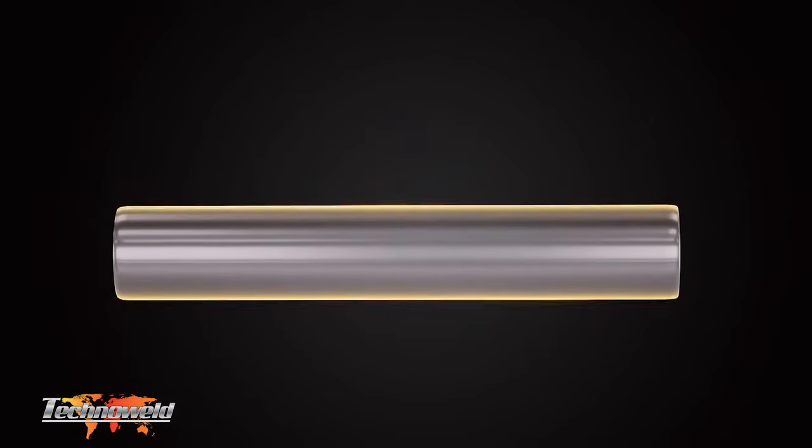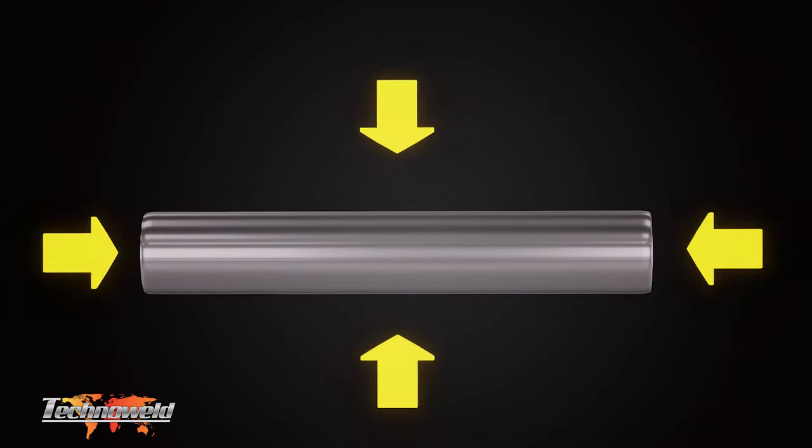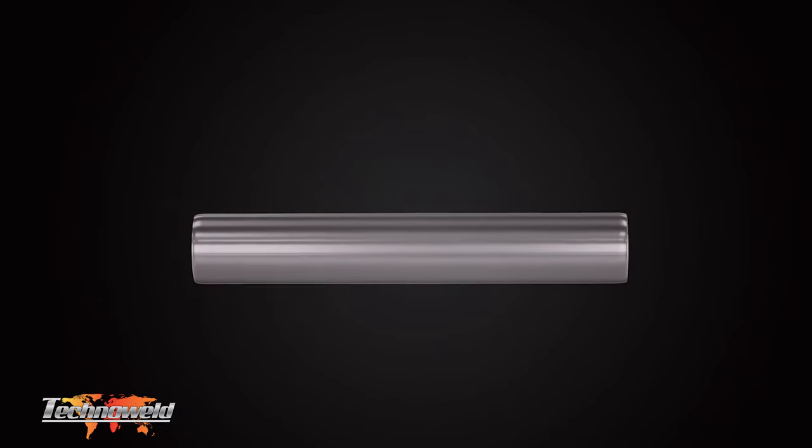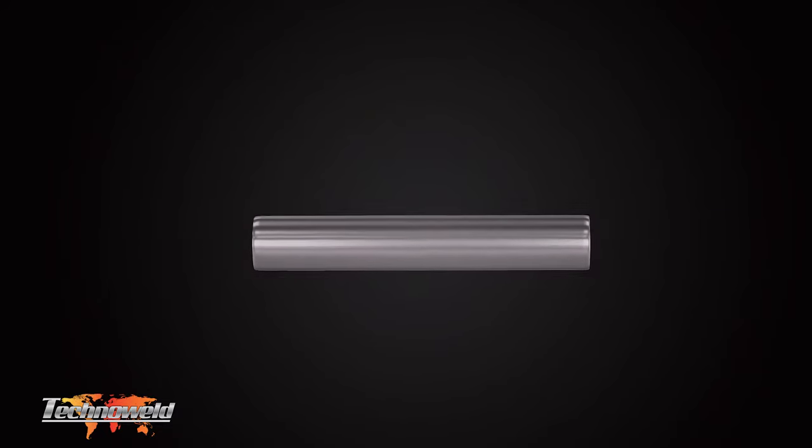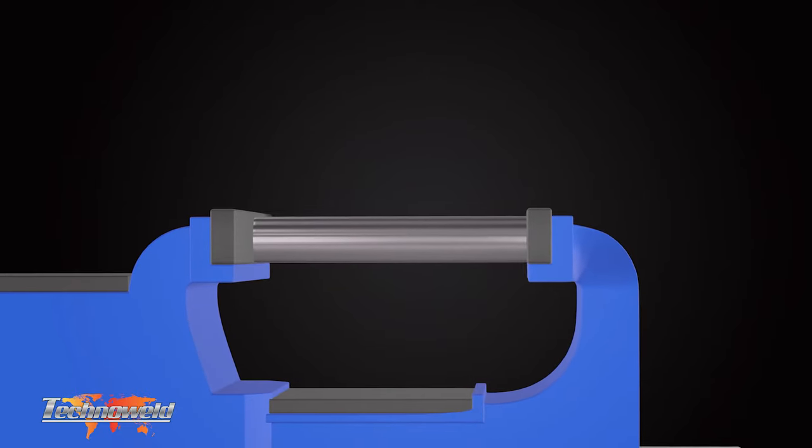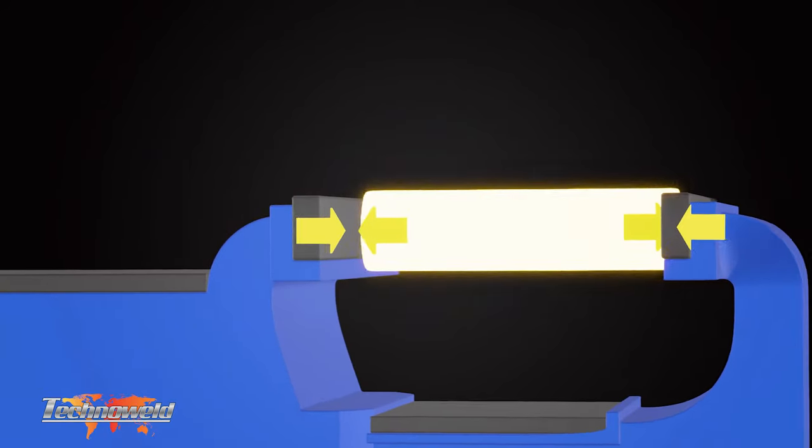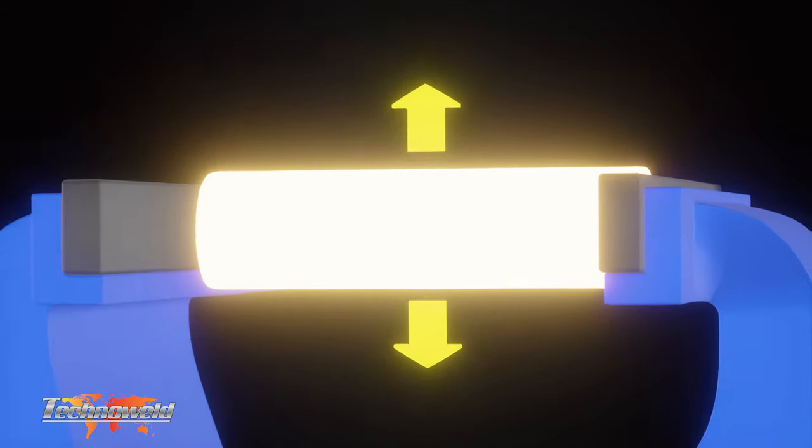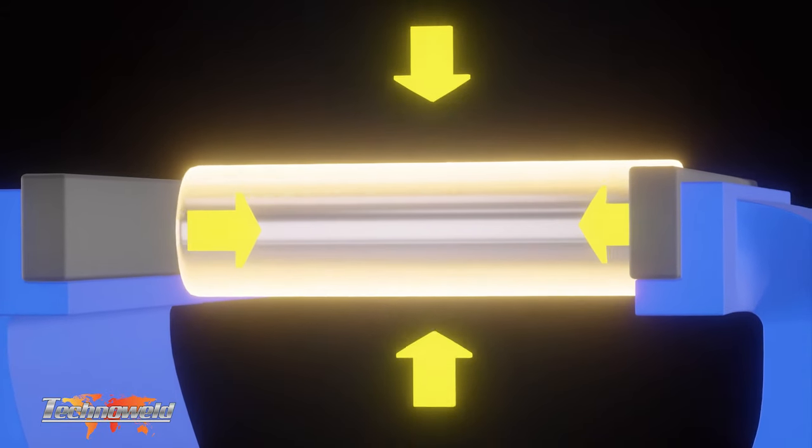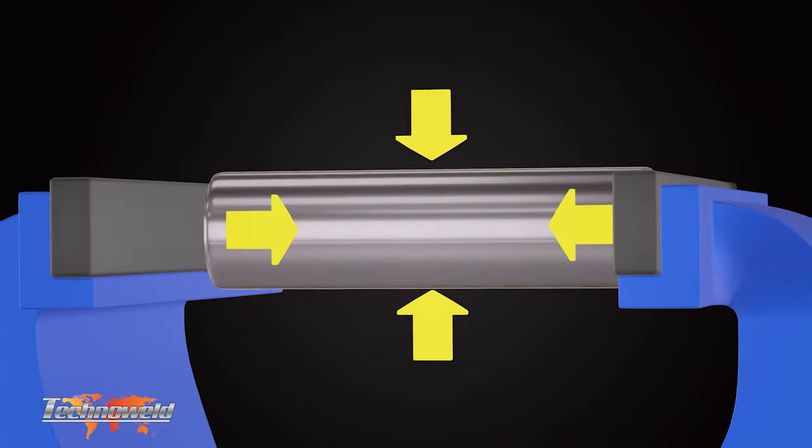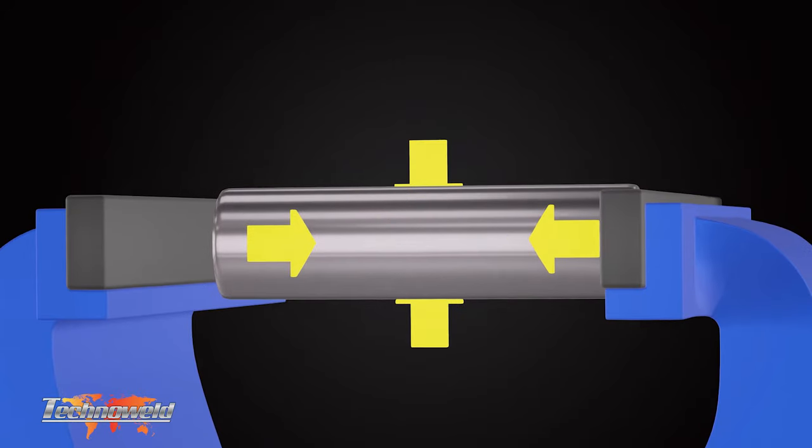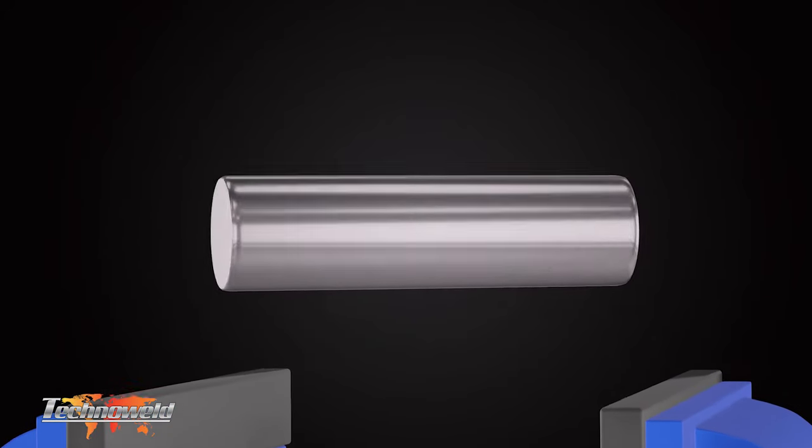But if we were to place the bar in the jaws of a vice, the vice will act as restraint on the ends of the bar during expansion, preventing it growing in length. When the metal cools and begins to shrink, the bar will contract in all directions. This means we ultimately end up with a thicker, shorter bar.